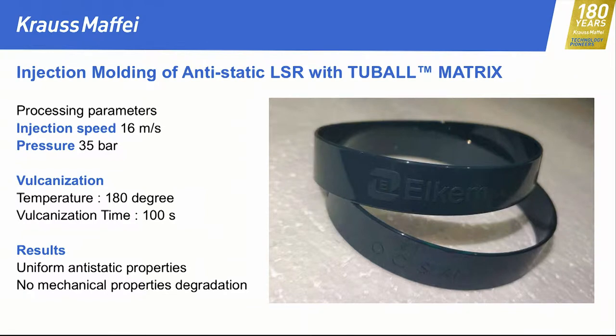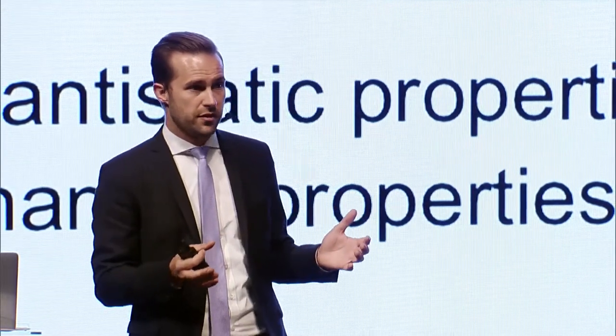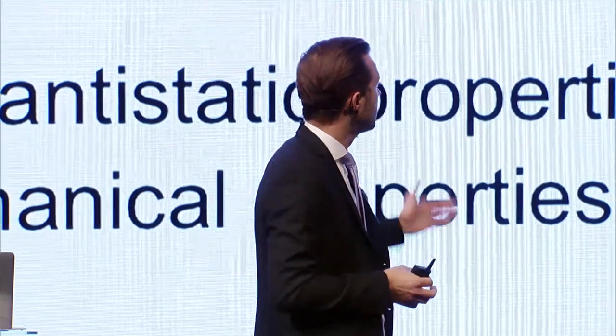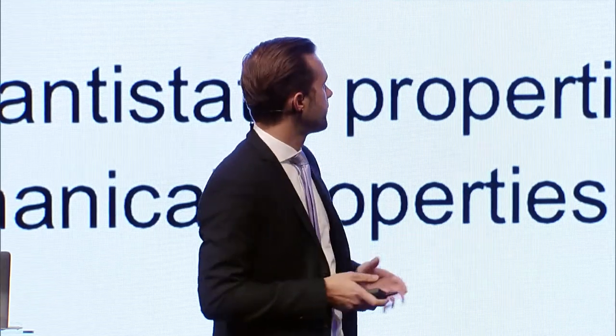So the vulcanization process, the curing process, is not negatively influenced, as I already said, with a vulcanization time of 100 seconds at 180 degrees. We have uniform antistatic properties. We do not have any color changes here, and also especially the mechanical properties, which are for the customers one of the most important things because they just need to be fulfilled. We do not have any challenges here with the Tuball material and have really a great production with that.